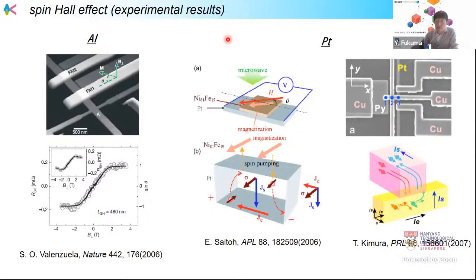After the theoretical prediction, we can observe the experimental reports. The first demonstration of the spin Hall effect was done in a semiconductor. After that, there were reports for the metal materials. For example, this is the first case for aluminum. To observe the spin Hall effect of aluminum, they used this kind of lateral spin valve structure. They inject the spin current by using this kind of ferromagnetic electrode. Then the spin current is injected in the aluminum wire. Then there is a conversion from the spin current to charge current, and they detect the voltage.